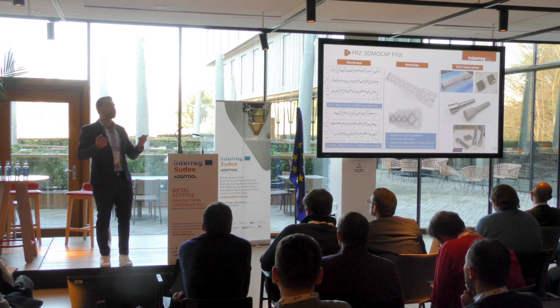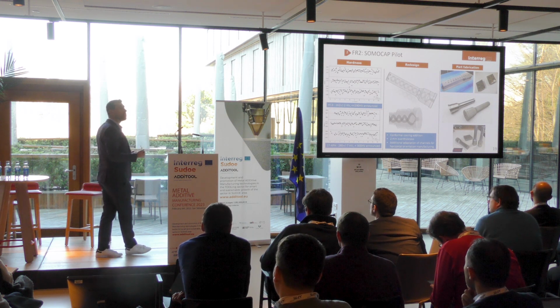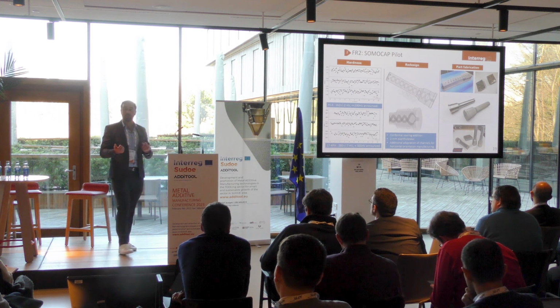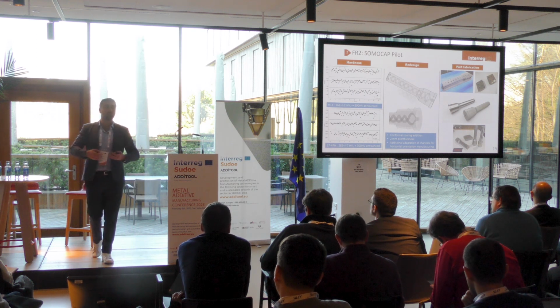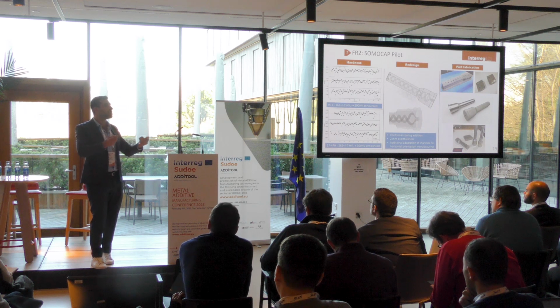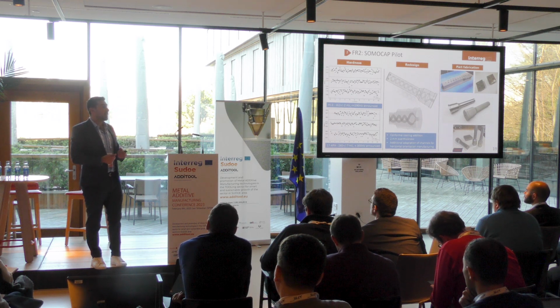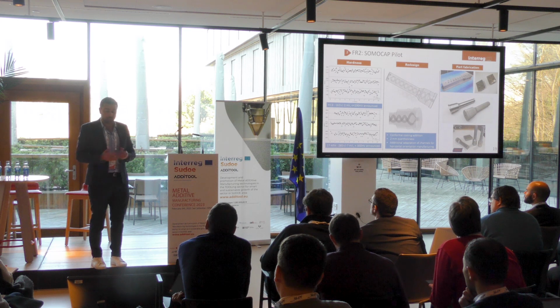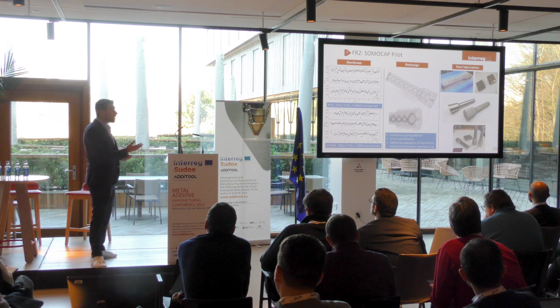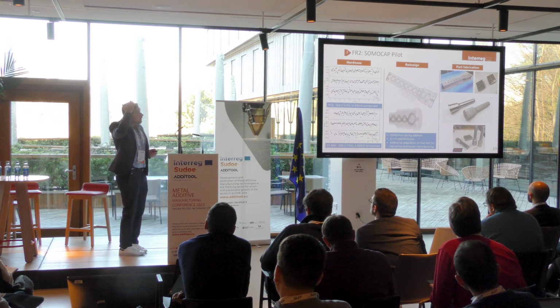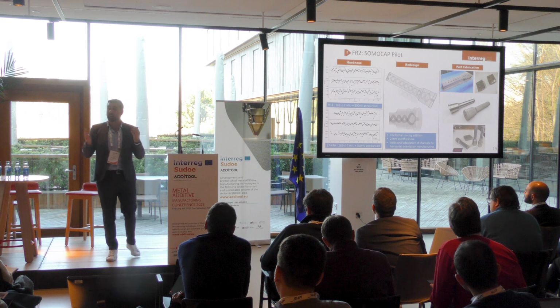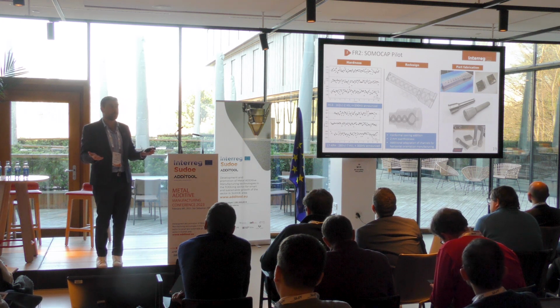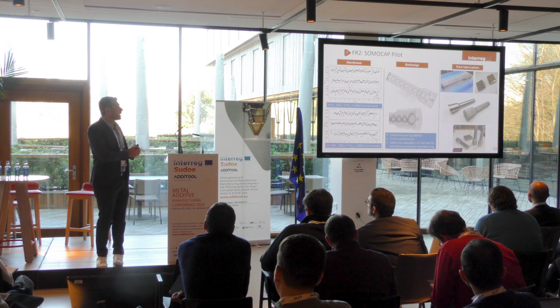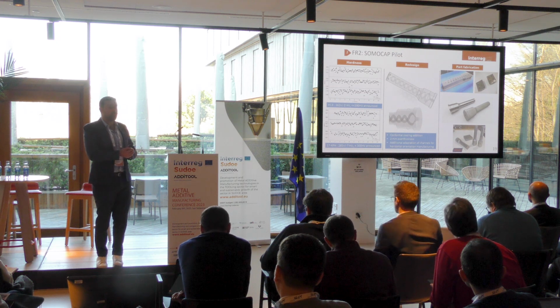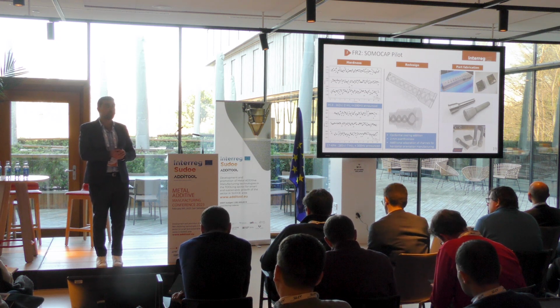So you have less polymer, less material to remove during debinding, less deformation, and it's an aqua technology so you don't have vaporization or smoke in the oven. So it's very interesting. It's Canadian, and they accept to manufacture for us a part that is actually being tested directly on SumoCap. I don't have the results yet to present, you will have them at the end of February. But this is something very interesting.